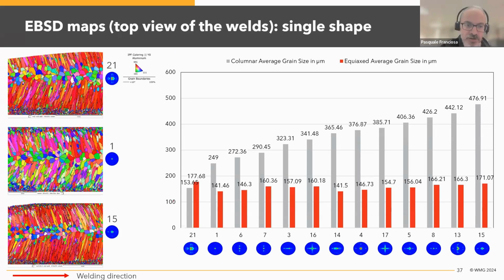So now starting from 21. So 21 is the forward triangle shape. Going to 15. So 15 is like one spot in front and then one vertical line straight behind. We can see clearly grain refinement, and also quite visible is the refinement of the columnar grain. So comparing 1 and 15, as expected, this is true for any welding process, we have more equiaxed grain towards the middle of the weld, and then you have a stretched columnar grain on the side because of the heat transfer dissipation towards the top and bottom of the weld.